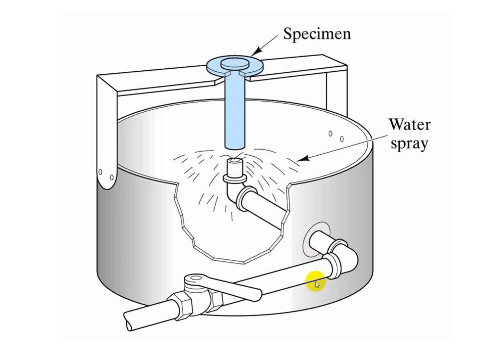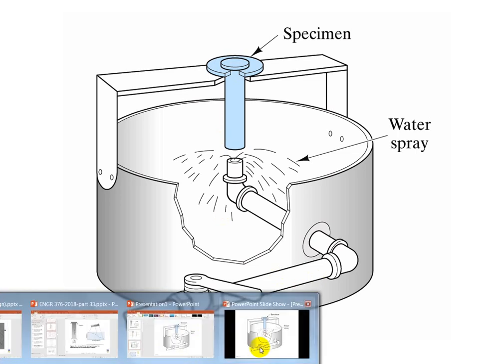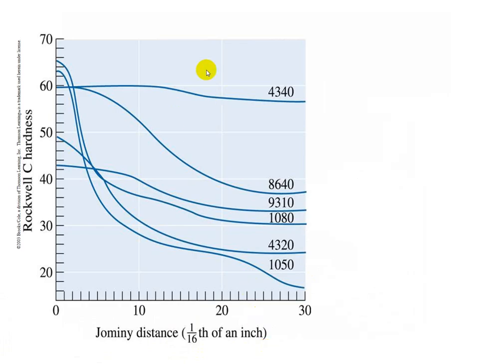Now when you go to the actual Jominy charts, in the x-axis we have the distance from the Jominy head. This is in millimeter or it could be also per inch, both of them. Obviously this is linear. And on the other side, we don't have it here but in the next slide you will see that this is cooling rate, either Celsius per second or Fahrenheit per second, and this will not be linear.